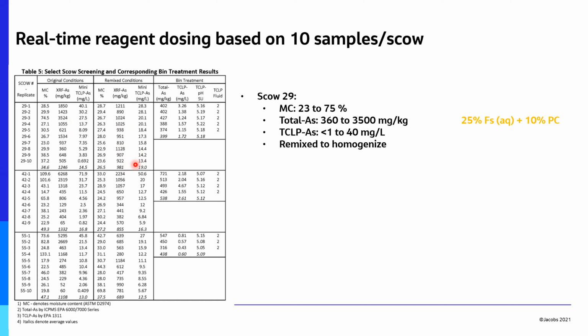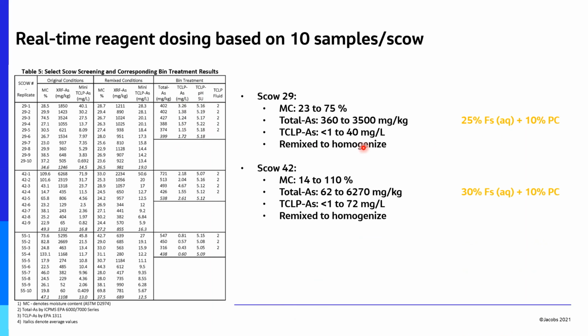Now on the basis of this, we treat it with 25% aqueous ferric sulfate, 10% Portland, and then here is our bin compliance testing before exporting for the site. You see that we had basically 3.26, 1.38. Our average ended up being 1.72. But if you had one failure on this, it had to be reprocessed, right? Our pH is, again, right in the middle of our targeted range, about 5.2. So this was a pass. After we rehomogenized the scow, let it sit for another 6 hours, brought it back, retested.